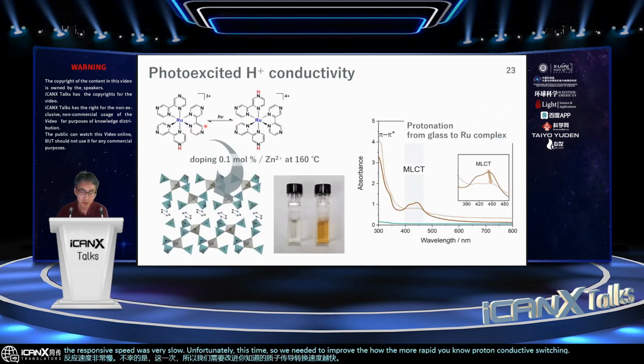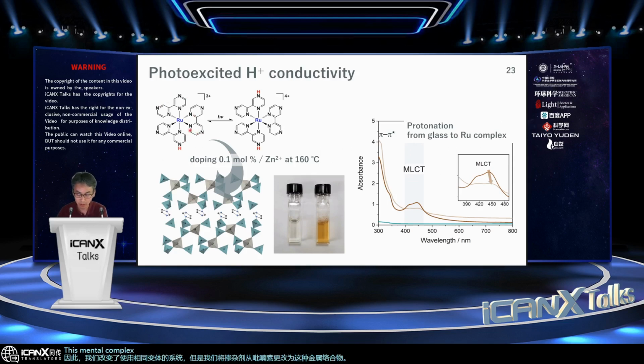So we changed the system. We use the same MOF glass, but we changed the dopant from pyranine to this metal complex. This ruthenium metal complex is also very well known to have a proton and release the proton by UV irradiation. And so this actually works very well. So we doped a pretty small amount of this molecular dopant into the melt state.